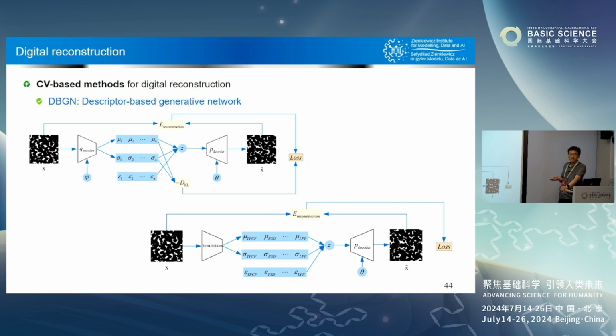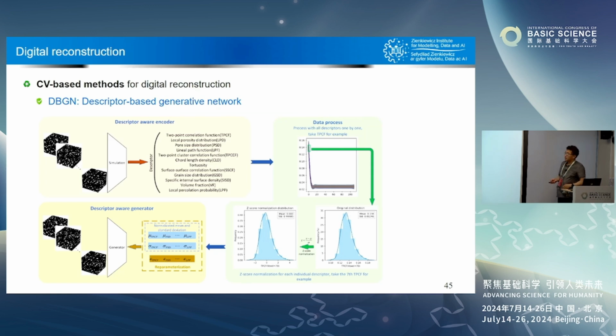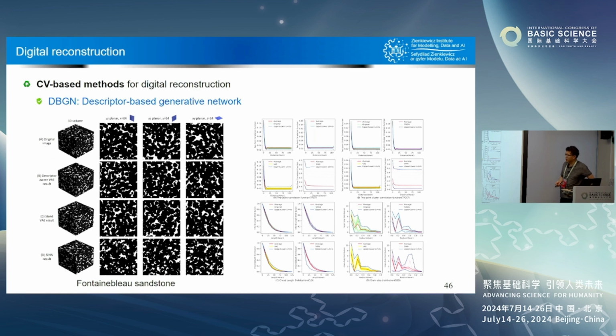These descriptors have physical meaning, and that is well understood by engineers. By doing that, we basically take the real feature space to the image and do the iteration. So in this process, we can explicitly monitor the convergence process in terms of your features, how close you are getting to your target. And the consequence is your result either doesn't converge, then you know you failed, or when it converges, you know you have a good result. It's a good one, for sure. There's no need to do an examination of that. And of course, the cost is smaller because you don't need to train that neural network anymore. You only train the decoder. So the cost is reduced by half. And these are some examples that show the difference in accuracy compared to the standard generative AI model.